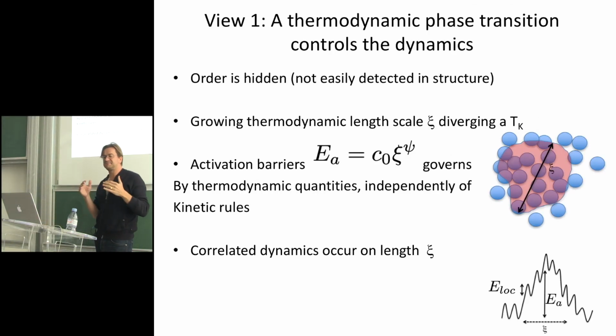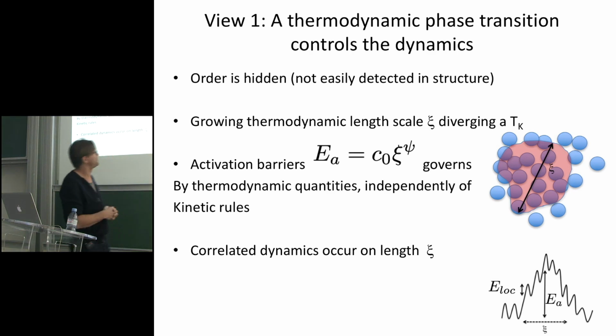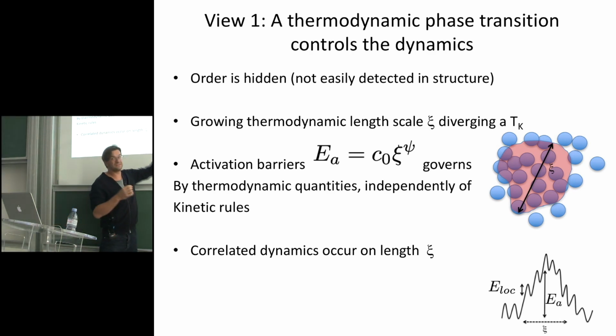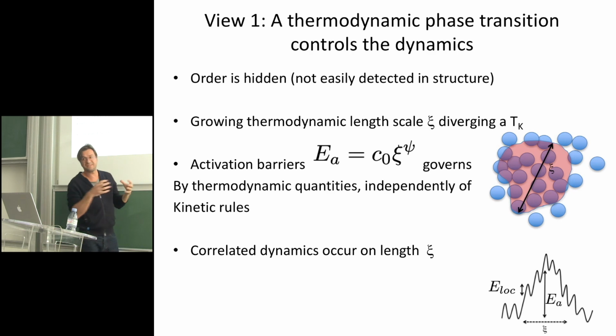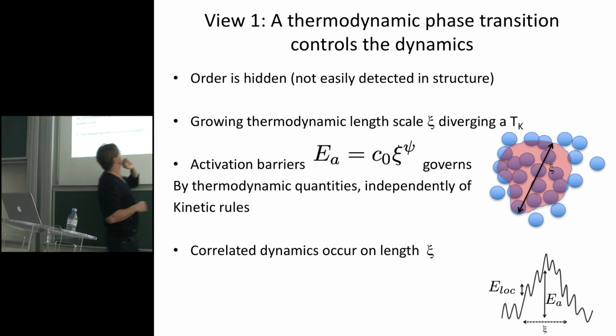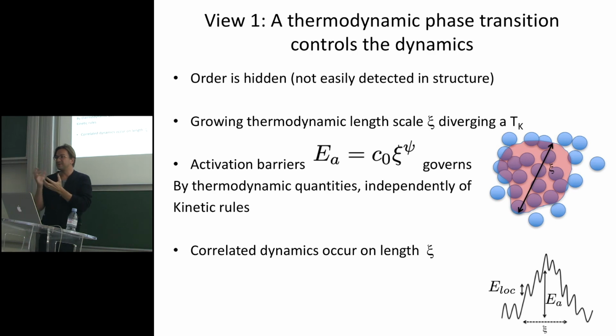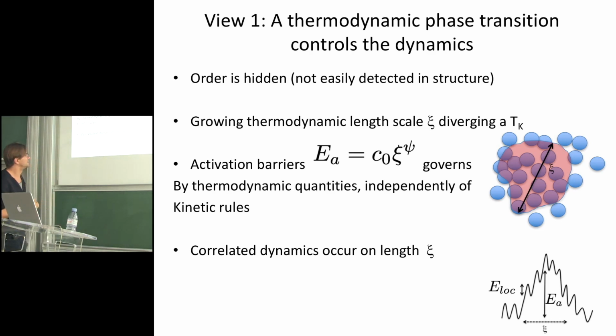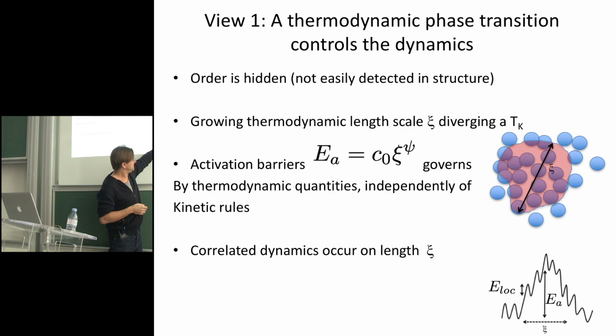So let me just tell you a little bit more about the different theories that enter in those different categories. There is one view, which is that really underlying the slowing down of glasses, there is a thermodynamic phase transition. There is some kind of order that grows in the system. Now, this order is hard to detect. You need very astute ways maybe to detect it. But there is a structure that's growing in the material. Because of that, the dynamics become more correlated. That's just this length scale xi. And the barrier to break the system and relax is typically a power law of this length scale. Okay, so that's one of those models where it's easy to relax a few particles, but you need to do something very cooperative to really relax.